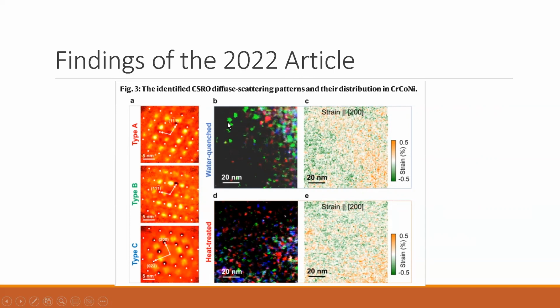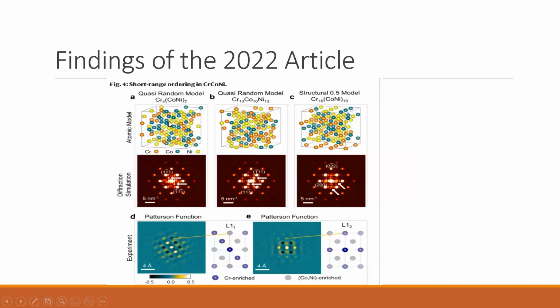So as we can see, for water quenched, there's a lot of type B's, and for type A's, the CSRO clustering, the nanoclustering of these alloys is as dense in water quenched, but in the heat treated, they have more room to grow and find room for themselves in the lattice mixture, and there are more type A's in the heat treated one. And as you can see, this is an illustration that shows different chromium, cobalt, nickel compositions and their short range ordering. So it's not totally random.